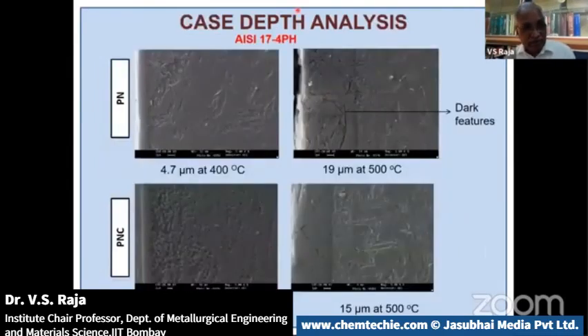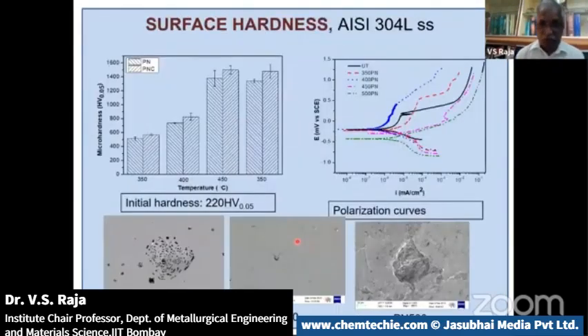You see here kind of coatings, you can call them nitriding processes. This is called plasma nitriding, and this is called plasma nitrocarburizing. Okay, so that's what you can do, right? So you can get the hard surfaces here, and these hard surfaces have unique properties of hardness as well as corrosion resistance. I can increase the hardness values, okay, but again, there are various operating conditions, temperatures, concentration of the species that are going to be added. A lot of variations are going to be there. The net result is it is possible to tailor the surface to have different hardness values, and then a corresponding change in the corrosion resistance of the surface.